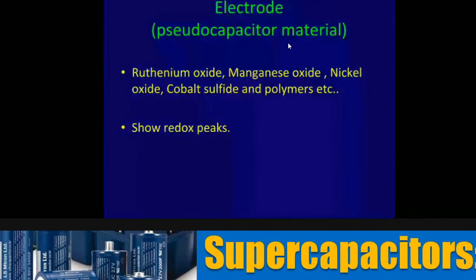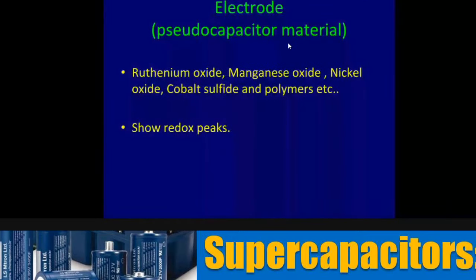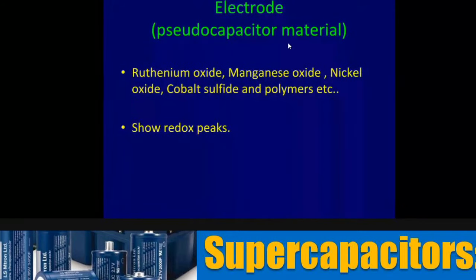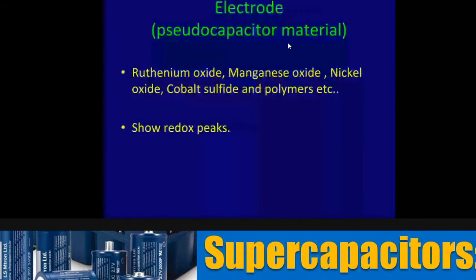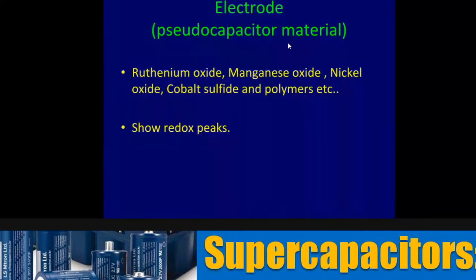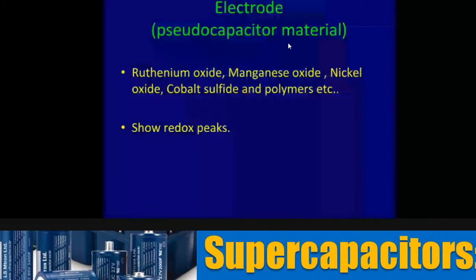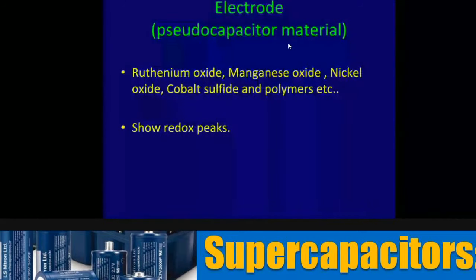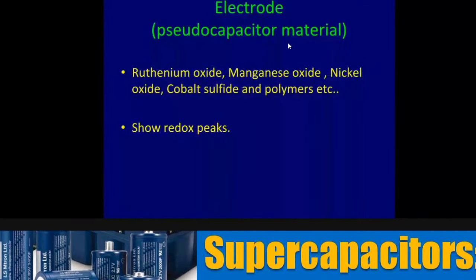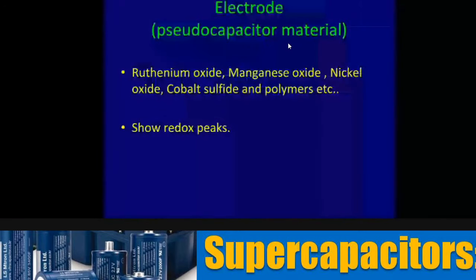Mostly people use transition metal oxides, polymers, and so on. The major problem with polymers is that when you keep on cycling it, the polymers have a tendency to shrink and bulge. Something like most of the viewers today would have seen with the old cell phones. You keep on charging the cell phone, probably after 6 months or 1 year, you will see that the back of the cell phone will be bulging, and when you open it, you will see that the battery shows bulging. And so still, polymers give us a little difficulties. But when we move over to other materials, we want to see and examine which are all the materials that are suited for this kind of application.